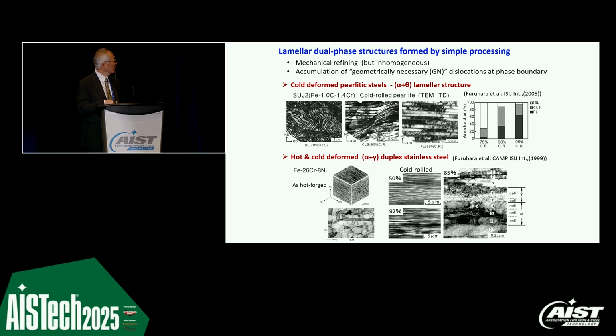And this is our case. We apply heavy cold rolling. We can obtain cementite lamella elongated parallel to the rolling plane. And we can get a similar one starting from duplex stainless steel after hot forging and cold rolling.